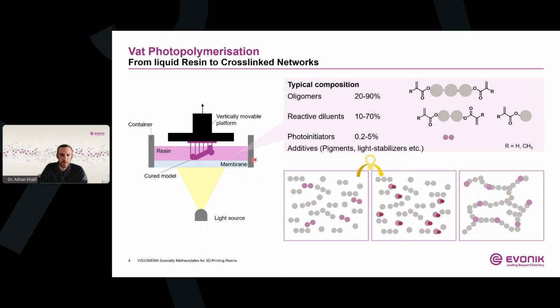So in general, in a vat photopolymerization, liquid resin is selectively exposed to light and converted into a three-dimensional solid structure in a layer by layer manner. The resin itself is typically composed of 4 major building blocks. So we have oligomers that provide the primary mechanical backbone. Then we have reactive diluents, which can be monofunctional monomers or multifunctional crosslinkers that can control the viscosity and of course also participate in the network formation.